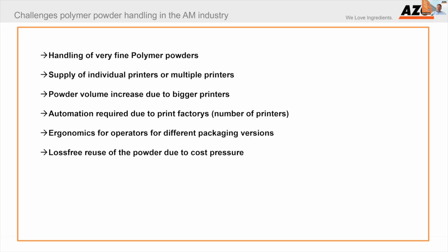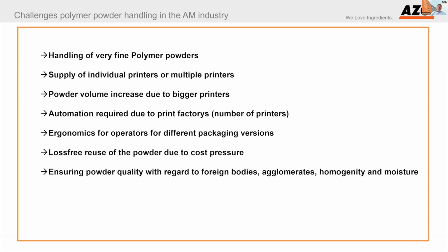Also in the polymer industry, there is high cost pressure in production and in terms of efficiency, so there is a need for that. Ensuring the powder quality means foreign bodies and agglomerates are not allowed. Homogeneity is one of the most critical issues in a printer. If you look at the printing process with polymer powder, there's an additional issue, which is static load of the powder. That's typical for a polymer powder. It gets a static load, and you have to get rid of that because the printer couldn't work with a static load, and the powders will not work.